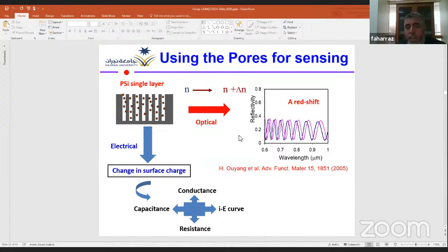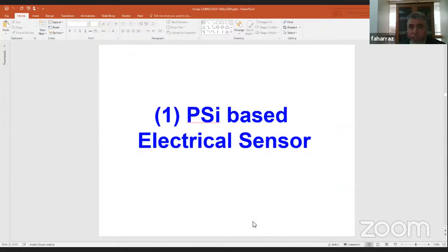You can follow this change in optical properties by measuring the reflectivity, and you will get some red shift or blue shift depending on the physicochemical properties of the target analyte. In the other way, upon infiltration of the target analyte into the nanopores, some change in surface charge will occur. This will change the electrical properties of the porous silicon. You can follow and measure this electrical property change via measuring the capacitance, conductance, resistance, or I-V curve.